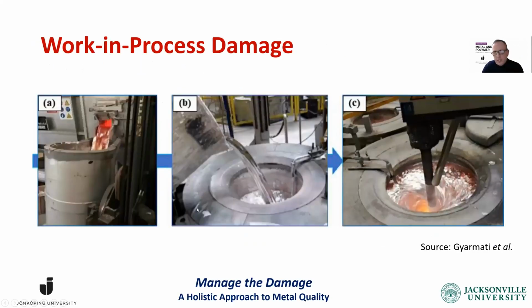So at every stage in the process sequence, so you have the big furnace, take a sample, take an RPT sample, take a tensile sample. After the melt transfer, take a sample, RPT sample, tensile sample. Second melt transfer, again, before, after, and all of these. You don't need to do it all the time, but you need to do it every now and then. And it's not very expensive. It does not interrupt the production, but you need to get data. You need to understand how much damage you're giving to the metal.